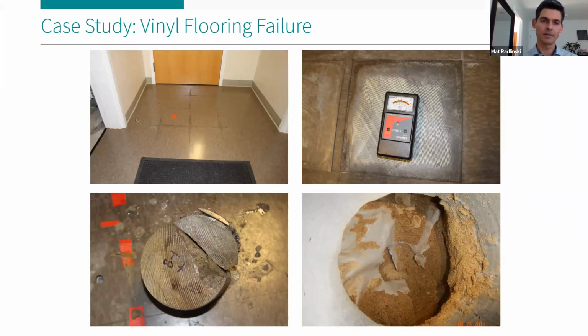From a core hole, we extracted right at the interface of the damaged and undamaged area. The areas that you can see that corresponded to moisture damage were underlain by new concrete infill slab that was installed to just fill those trench locations. And right below that slab, there was no longer a moisture vapor retarder. It sort of underscores the importance of installing it.